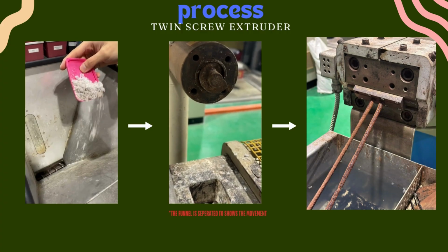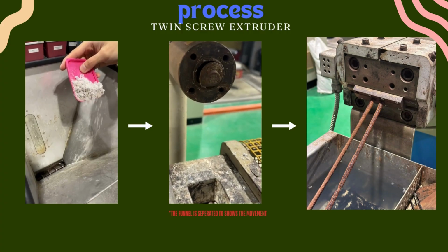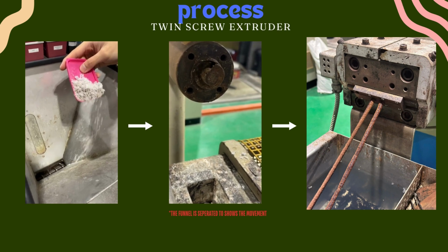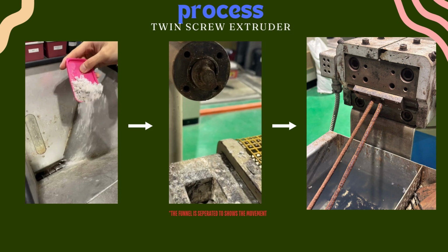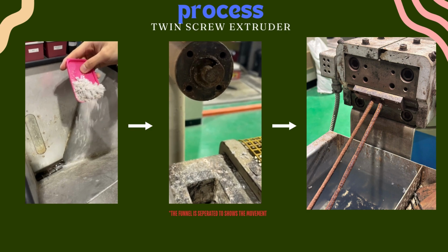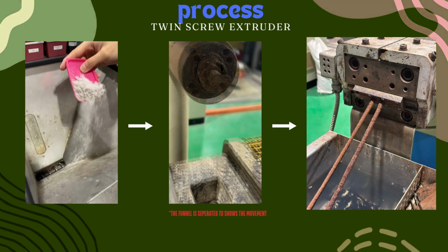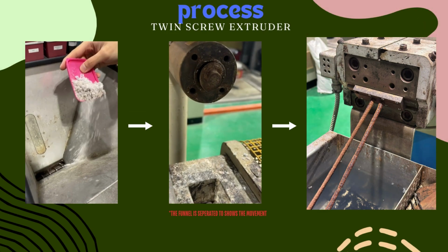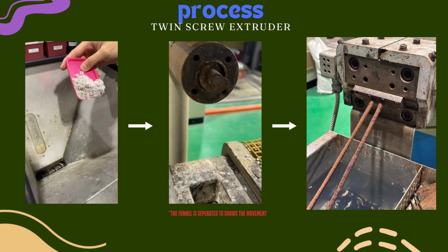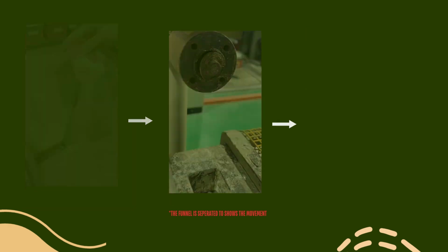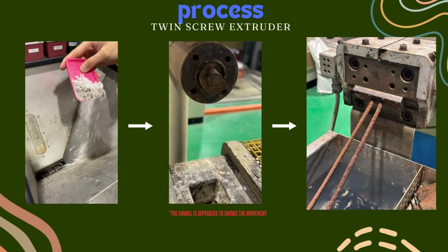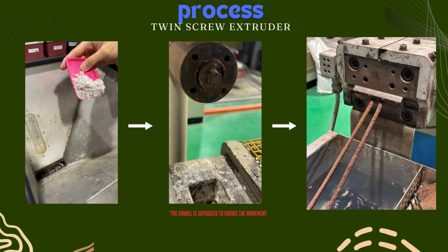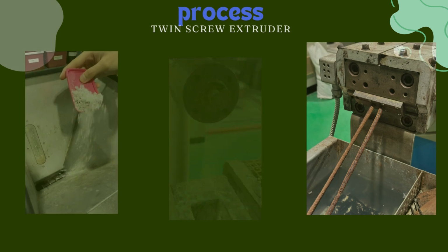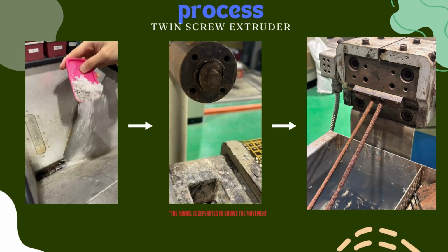This method ensures that the recycled PVC and Kenaf fibers are effectively blended, resulting in a uniform distribution of the reinforcing material within the polymer matrix. The process begins by inserting all the mixture of the formulation into the loader, where the screw mechanism gradually pushes the mixture towards the first chamber of the twin screw extruder. As the material moves forward, it undergoes a controlled heating process, with the temperature steadily increasing as it advances through each subsequent chamber. This precise temperature control ensures proper melting and mixing of the composite materials until the mixture reaches the final chamber, where it is then extruded through the die, shaping the material into the desired form.